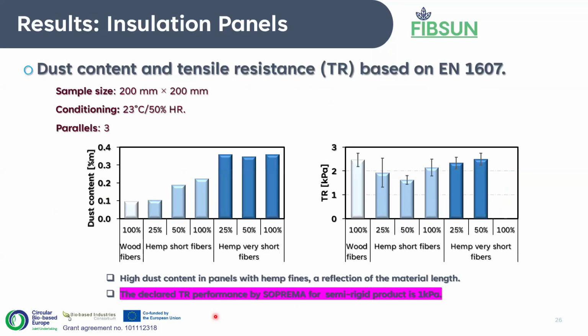So without further ado, we look at the panel properties. And as I mentioned previously, we decided not to move forward with the super short fibers, the very short fibers. We noticed in general the high dust content in the very short fibers from the panel. And this is, of course, due to the short fiber length, but also the inability of these fibers to achieve the target thickness.